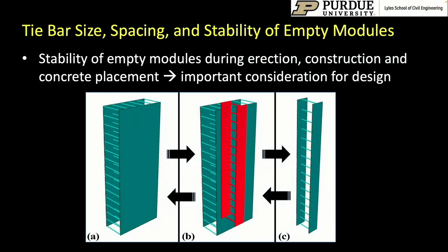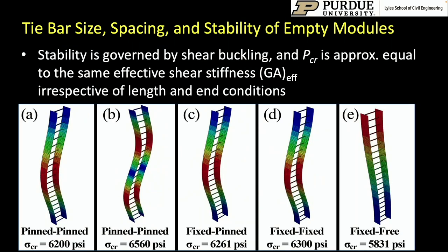And then we started looking at the stability of this empty module for construction level loads, and we found something fascinating. We found that the stability of this empty module is also fully governed by that same effective shear stiffness. This stability was found to be governed by shear buckling, and P critical for these empty modules was equal to GA effective, irrespective of the length and the end conditions.